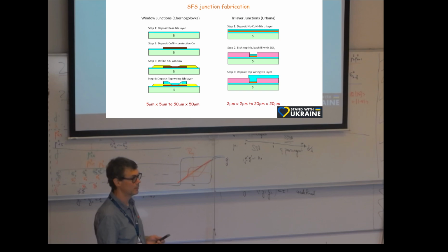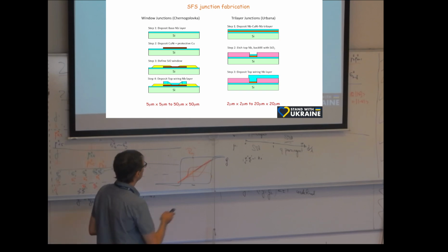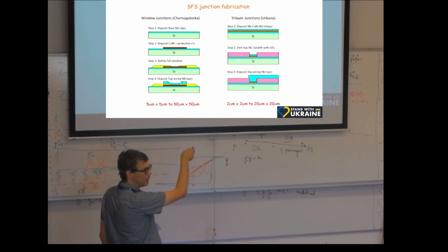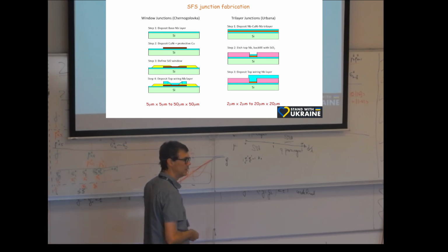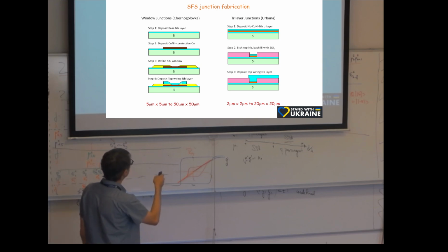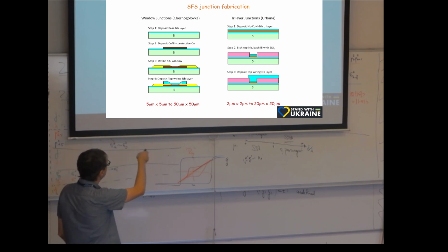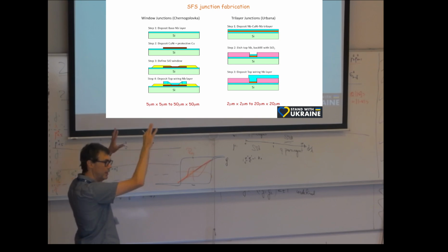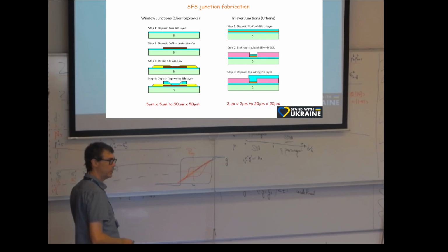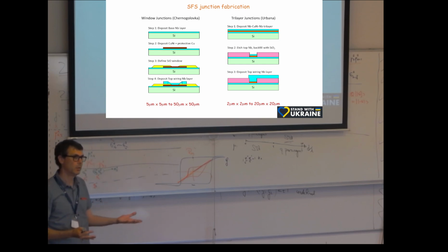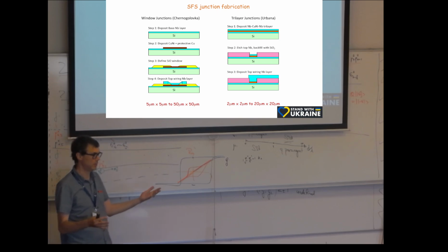Yes? How do you insert the bottom electrodes, like for the low state? Right, so somewhere far away, you can just put the contact directly to it. How did they do the silicon oxide window? Here? So they made another pattern. I actually sent them all the patterns, how I wanted them. And so in this pattern, there is a polymer that blocks off this area, and this area, and this area, and then silicon oxide goes down only where it should be. It's like a flake of silicon oxide? Oh no, it's deposited in a vacuum chamber. It's sputtered, if you know what that is.